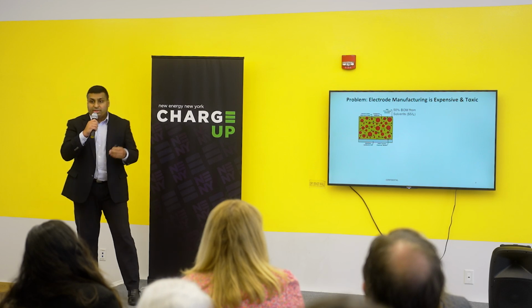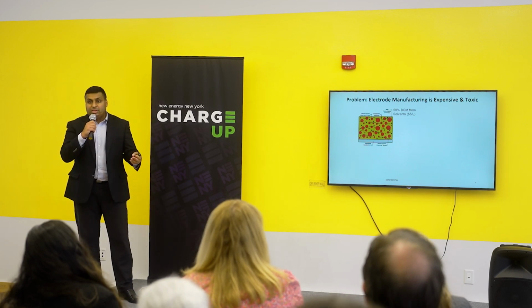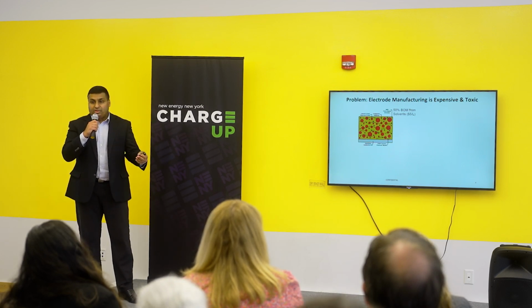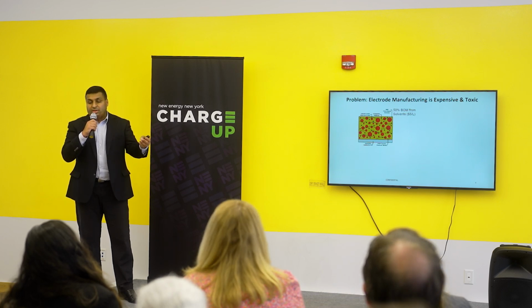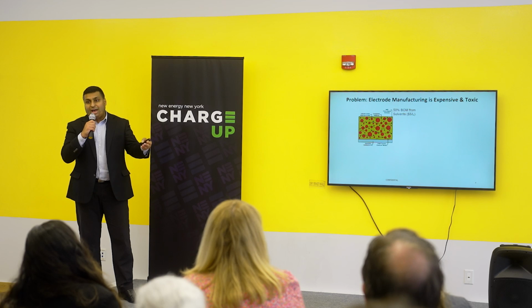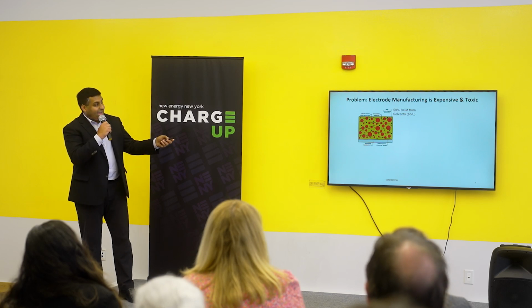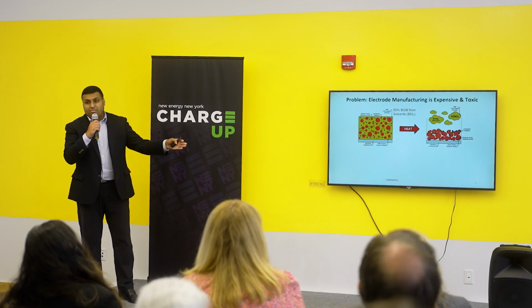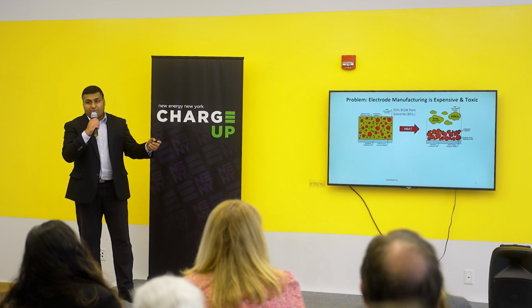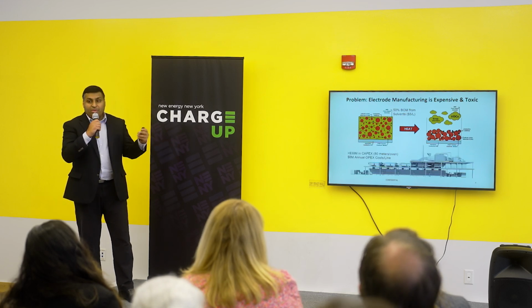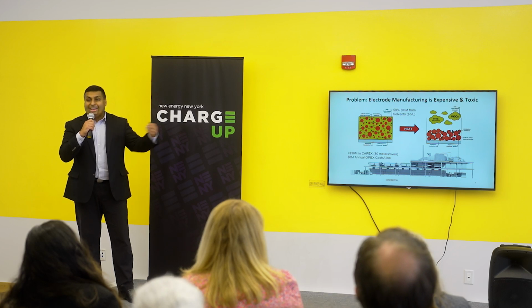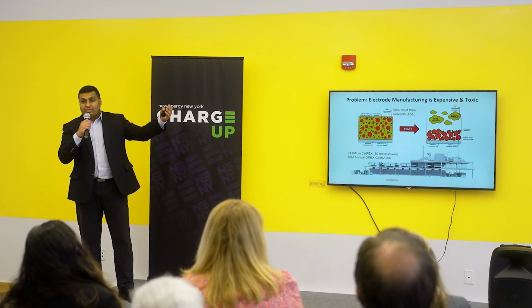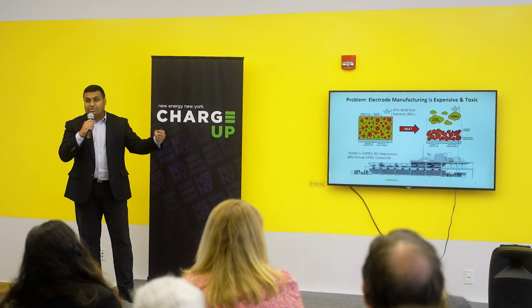And right now, everyone building these gigafactories relies on outdated technology that has not changed in 50 years, where we take these battery powders and mix them in polymers that require high-temperature toxic solvents, and then we use massive amounts of heat to remove that unwanted solvent. If you look at a gigafactory, the ovens to remove that are almost 80 meters long and about 2 stories high. So it's about $30 million, and you're spending another $8 million to remove this unwanted solvent.